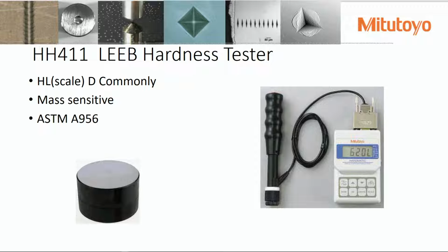Okay, there are 3 parameters though that must be met. You can't pick the 2 you want. You need a mass of at least 10 pounds because it's an energy; there's a rebound action going on. You need a surface finish of about 63 Ra, which is a nice ground surface. And you also need a wall thickness of 1/4 inch. That one, depending on the material, could be a little bit thin. If you have a brass or something that rings, you might want to have a little bit thicker than 1/4 inch. And sometimes you're allowed to use couplings to couple it to a larger, heavier mass.